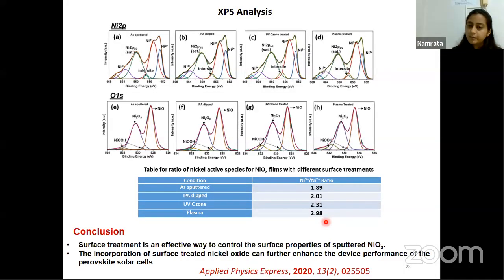It is important for me to mention here, even though these are not fixed ratios, we need to optimize it. We do not want too high of either of these. We need a balanced ratio, and definitely to achieve this ratio, we need to optimize the sputtering power, the plasma condition inside the sputtering machine, or the oxygen flow rate. So if we have an optimum level of Ni3+ to Ni2+ ratio, we can get a good